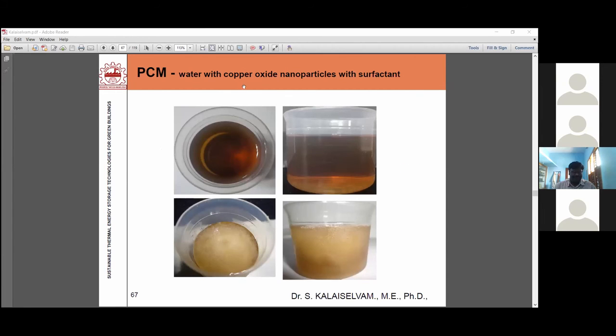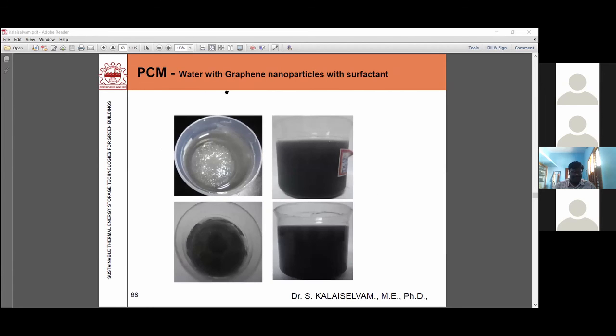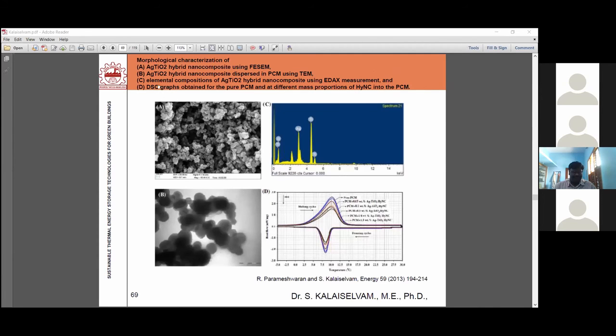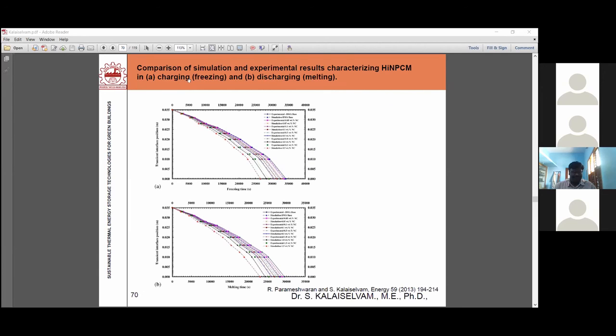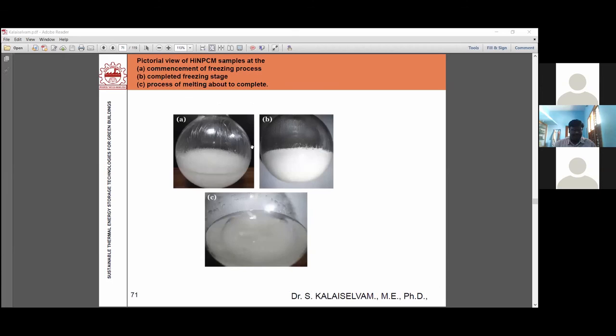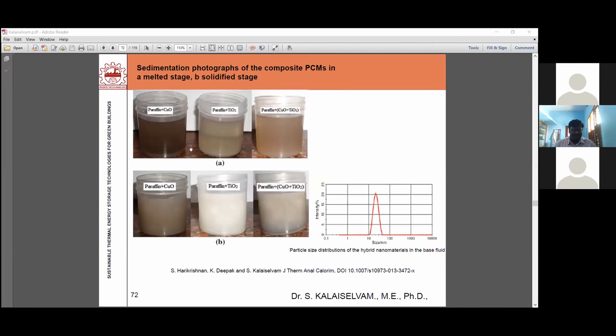And this is the PCM with water and copper oxide nanomaterial. This is a PCM with water with graphene nanomaterial. And this is the hybrid nanomaterial, that is Ag TiO2 hybrid nanocomposite material. And this is the solidification and melting curve. And this is the freezing picture of the hybrid nanomaterials. And this is again the sedimentation photograph of the composite PCMs, that is paraffin with copper oxide, paraffin with TiO2, and paraffin with copper oxide and TiO2. This is one solidification and melting curve.